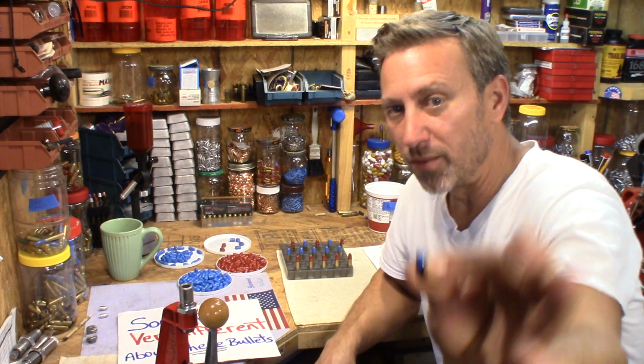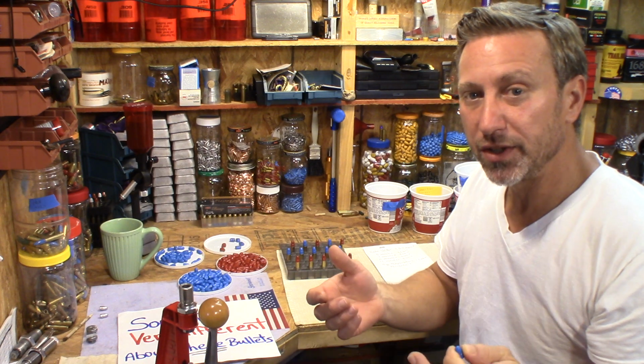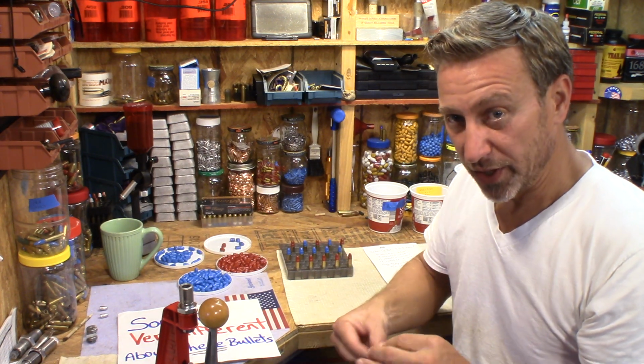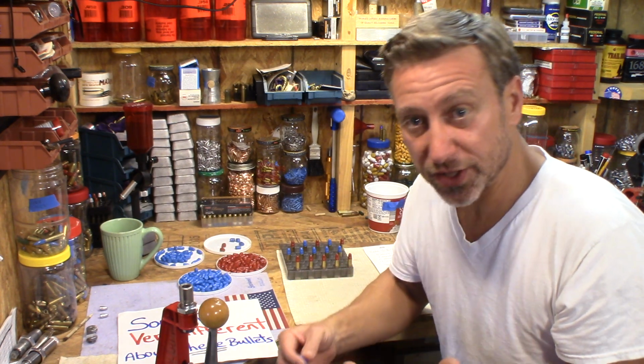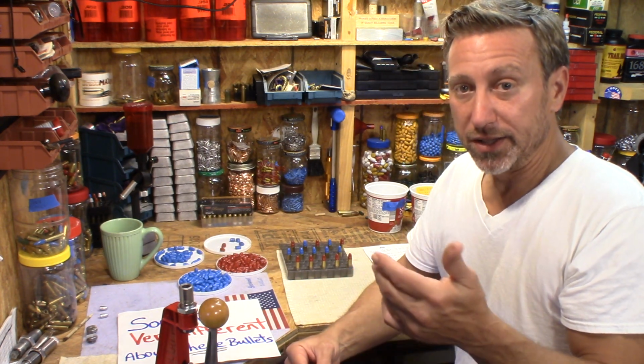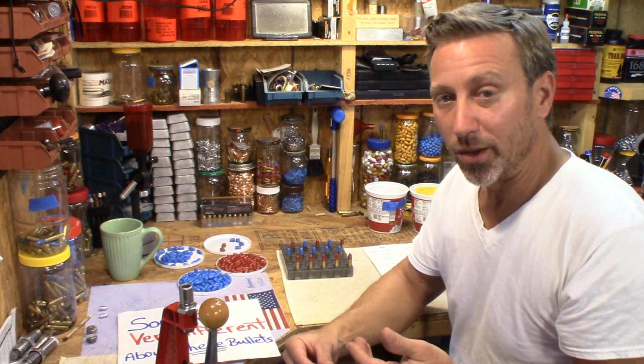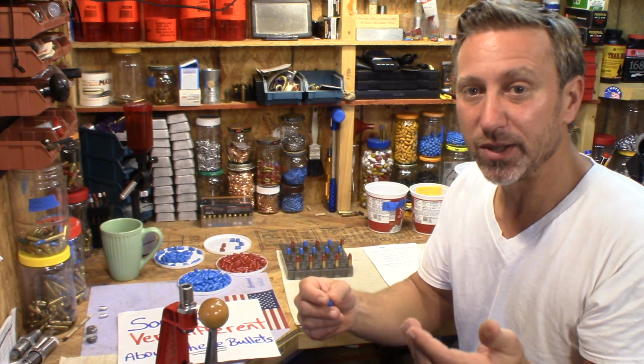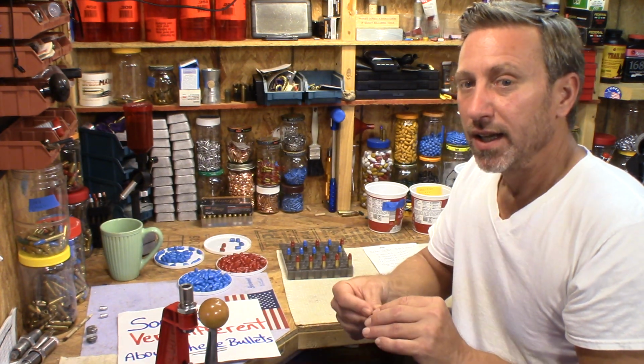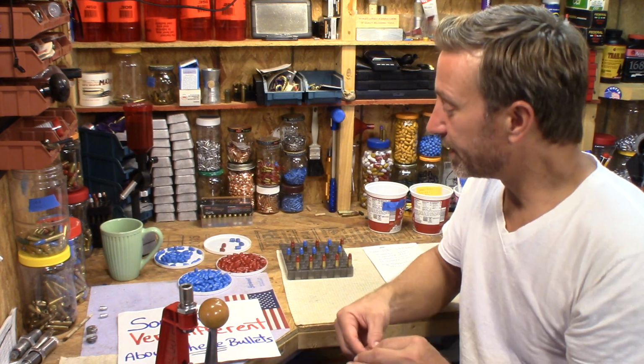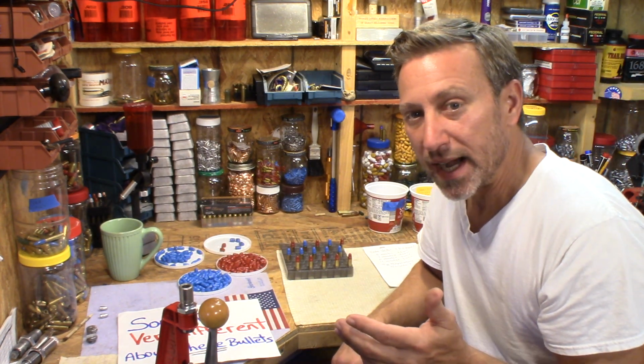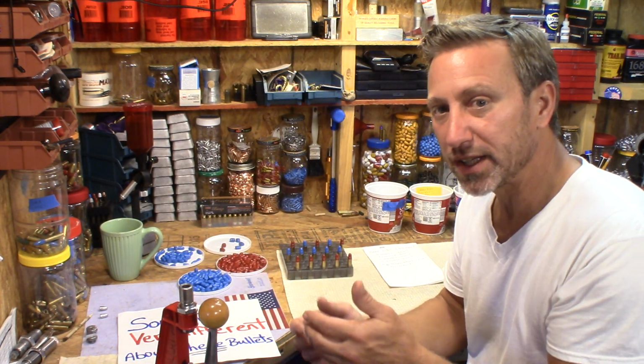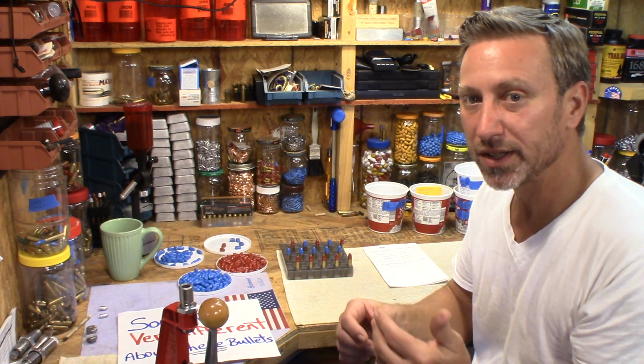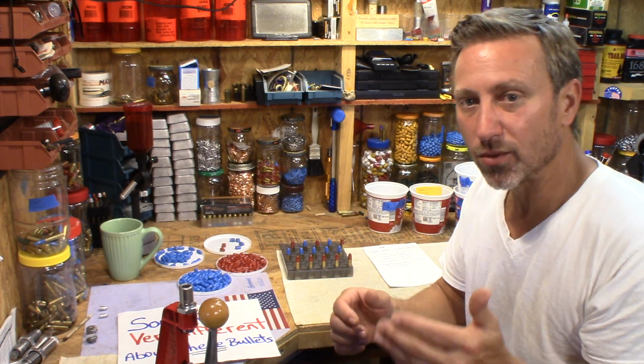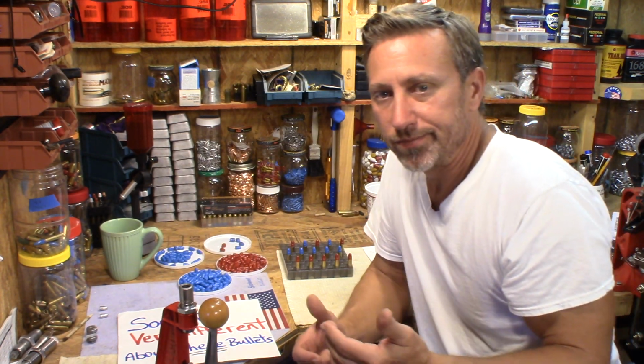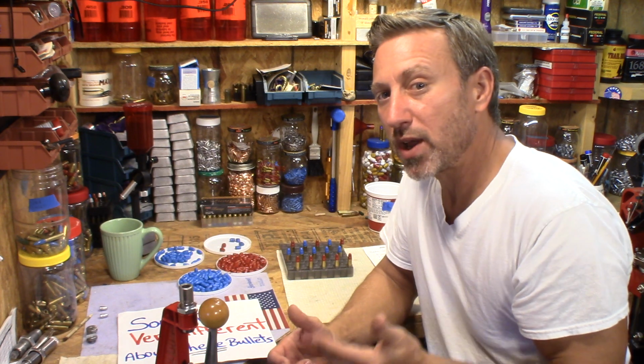we quench our bullets, we gain a substantial amount, especially if you're using like clip-on wheel weights, where you have your standard ingredients like antimony, tin, and arsenic. Those are usually common ingredients found in this type of lead, and we water quench them. And for instance, this particular, I separate my clip-on wheel weights from my stick-on wheel weights, and I end up with a pretty good hardness. After water quenching, I probably average about 21 BHN,